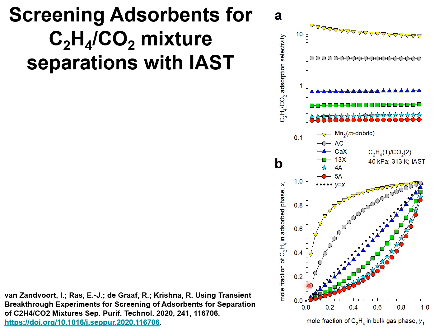The choice of activated carbon is understandable because the IAST calculations show that activated carbon is ethene selective. However, the IAST calculations show that LTA-5A zeolite is selective to CO2 over the complete range of feed mixture compositions.